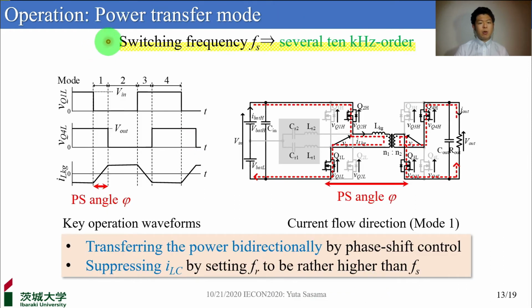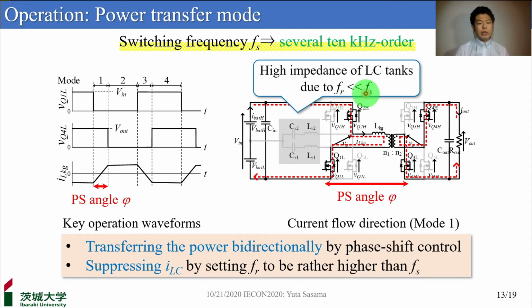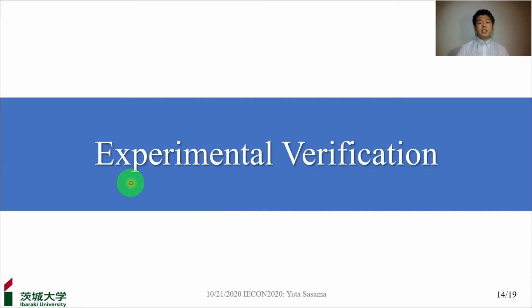This slide shows the operation of the power transfer mode. Similar to traditional DAB converters, the converter transfers the power bidirectionally by phase shift control. The switching frequency is on the order of several tens of kHz. As a result, the switching frequency becomes sufficiently higher than the resonant frequency, and the resonant tank has a high impedance so that it is possible to transfer the power with almost no current flowing through the resonant tank. By operating at different switching frequencies in this way, the two modes are independent.